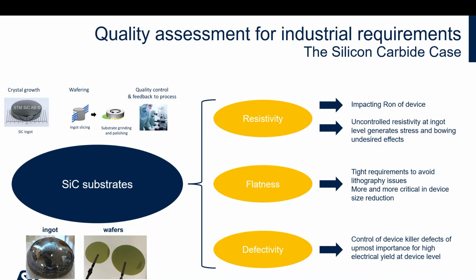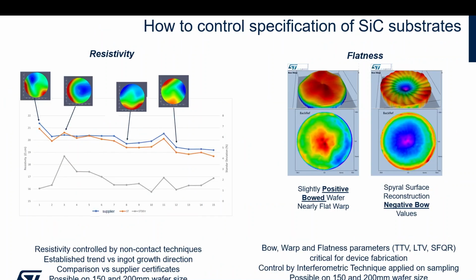If you buy from outside, this is a spec that the provider has to guarantee to you, and then you check it. If you produce inside because you are an integrated manufacturer, then you have to guarantee this yourself. So you need to control this. Controlling this means a lot of tools that are progressively becoming more and more fine-tuned for controlling the resistivity, controlling, of course, the topology, seeing if there is bow or warp or local thickness variation, which is a very important problem. So the manufacturing, before even starting the diffusion, the first step of deposition or lithography, has to consider this at substrate level.